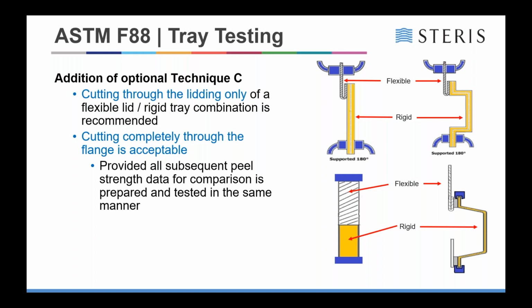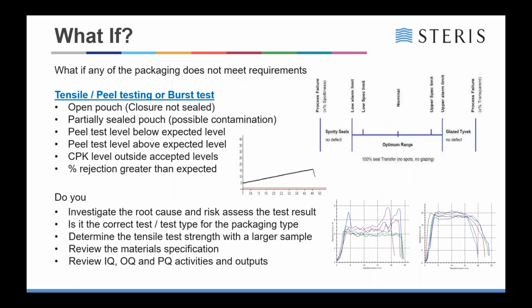Again, you need to look at what happens if something goes wrong. If you get an open pouch, if it's very badly sealed or a partially sealed pouch, what's happening to it? If the peel level is below what you expected, or if it's above what you accepted, then you have more problems. If the CPK value is outside the accepted levels, how do you actually address all of those?